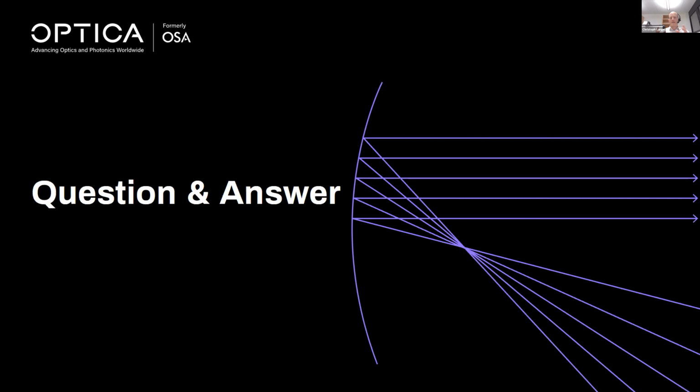The question is even, what is a single spin in this material if you go to just a fractional unit cell, which doesn't even make sense. The nature of this particular magnetism, this antiferromagnetism in this material, would not even exist anymore. So you need a certain minimum size of your domain. And I would say this domain size is ultimately given by the size that is still robust against thermal fluctuations. I guess that would be a limit, but that's small. That's a few nanometers.